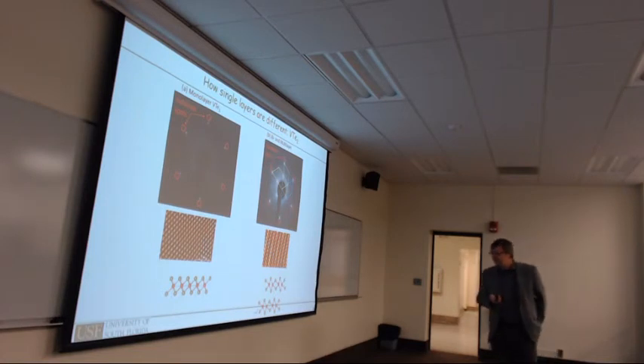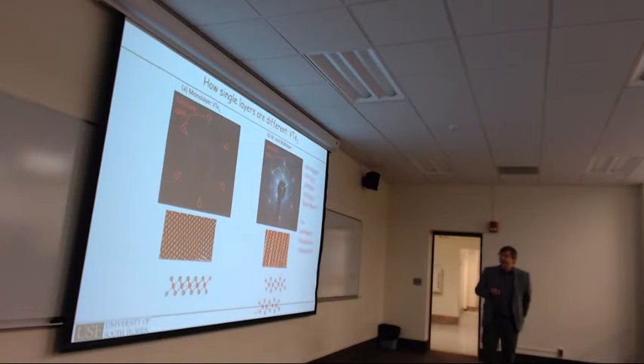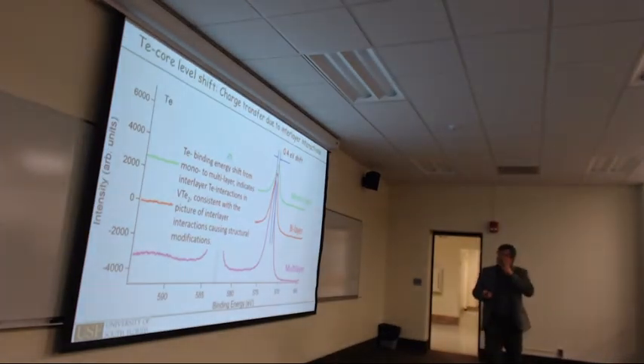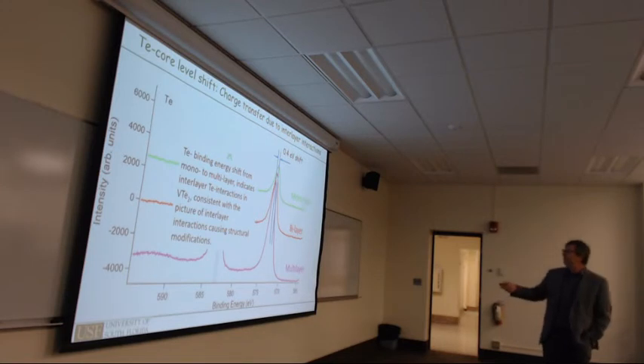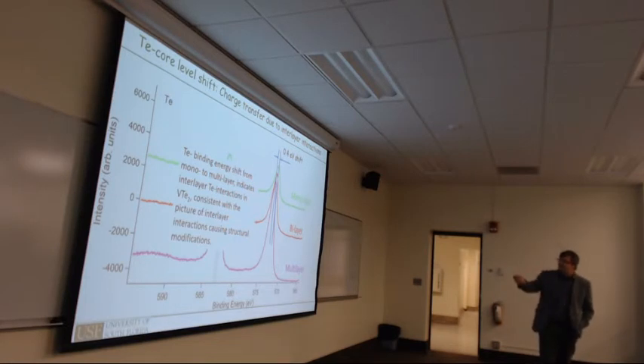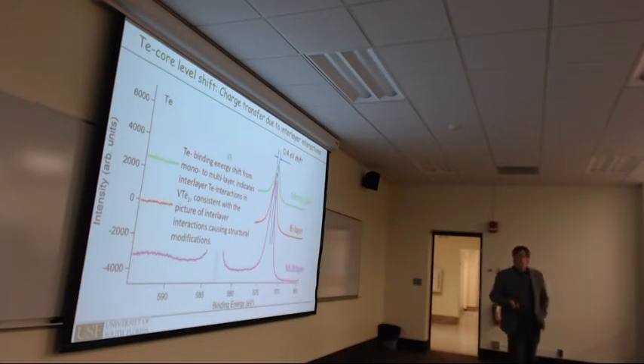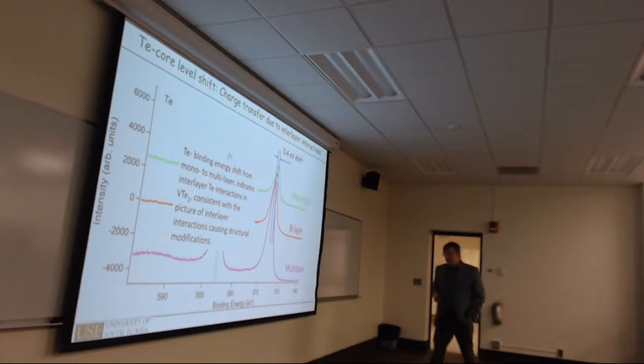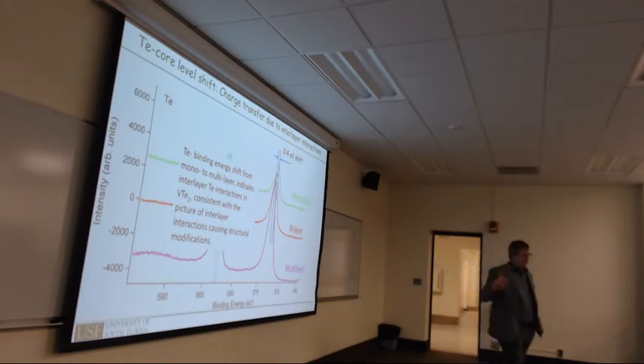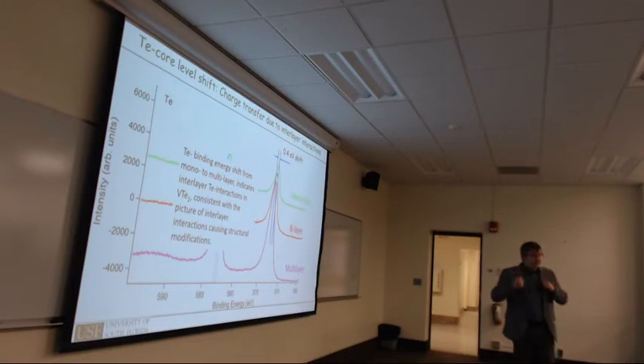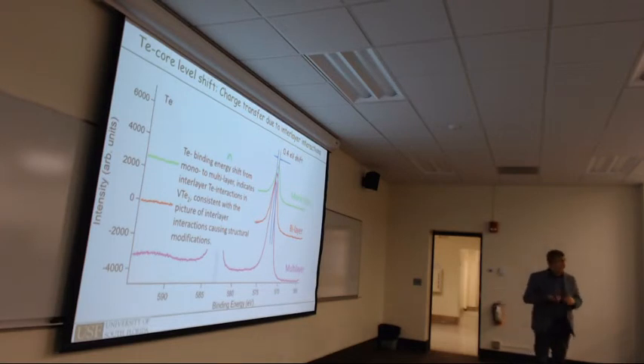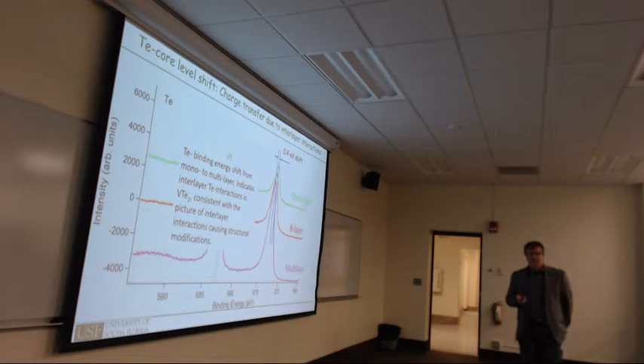Our theorist collaborators still work on that to work it out, but we have some experimental evidence for that. If you look at X-ray photoemission spectroscopy, the green line is for the monolayer, you can measure the binding energy of the tellurium core level, and then for bilayer and multilayers, this core level shifts quite significantly by 0.4 electron volts to higher binding energies, which suggests some charge transfer from the tellurium to the vanadium, and indicates that the tellurium atoms at the interlayer interact with each other to change the valency in the multilayer compared to the monolayer.